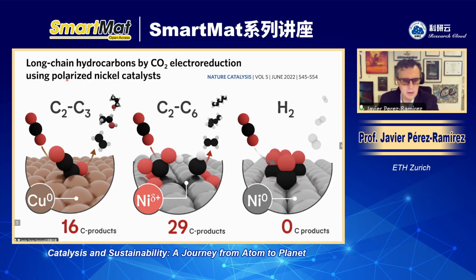CO2 electrochemically. What we have discovered in this publication is that polarized nickel sites, that is positively charged nickel associated with the presence of oxygen on the catalyst, could reduce CO2 into long-chain hydrocarbons exceeding the carbon number of classical copper catalysts, which essentially stop at C3, and we are able to make, with polarized nickel, up to 6 carbons in the molecule in one step.